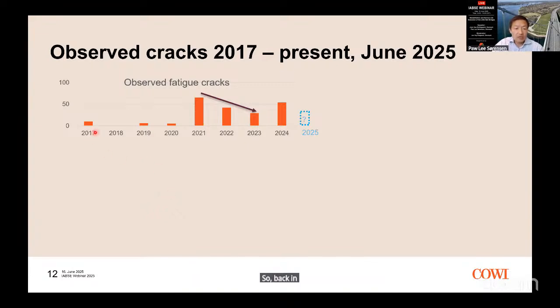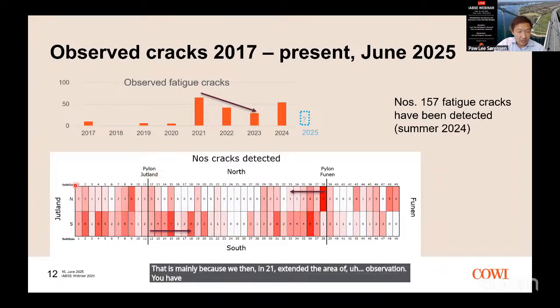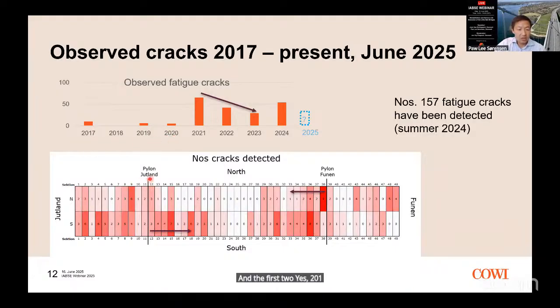So back in 2017, we observed the 10 cracks. We didn't perform the inspection in 2018. Then we saw a few in 19 and 20. And here in 21, you can see there's a big jump in the number of cracks observed. That is mainly because in 21 we extended the area of observation. You have an expansion joint here, one here, and one here, and one here. And in the first years, 2017 to 20, the main focus had been in the areas close to the expansion joint. But then when we extended the observation area, we see this large jump.